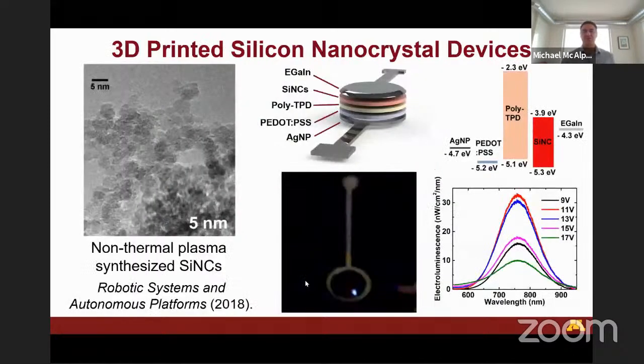And actually, when we got to Minnesota, the chair of my department was synthesizing silicon nanocrystals in a non-thermal plasma. And these silicon nanocrystals are 5 nanometers or less in size. And so that's actually below the Bohr exciton radius of silicon, which is 5 nanometers. So they emit light, unlike bulk silicon, which has an indirect band gap. So this is an example of us replacing the cadmium selenide with silicon nanoparticles. So this is the world's first fully 3D printed silicon-based electronic device.